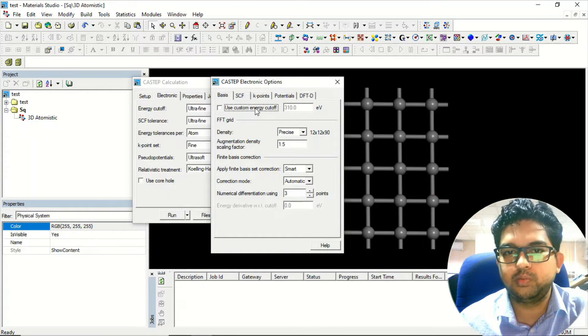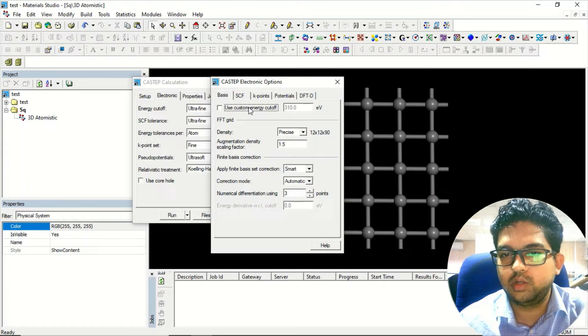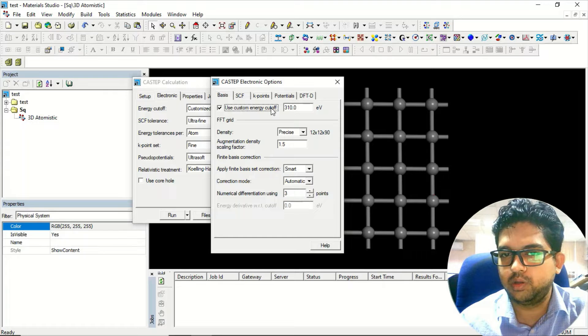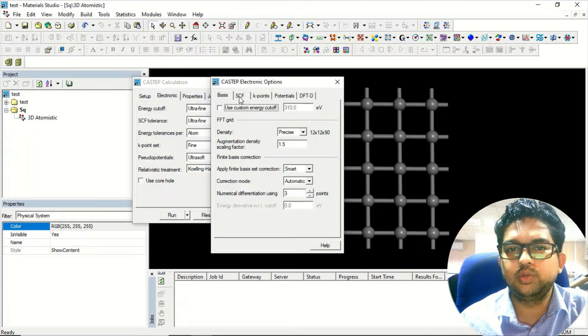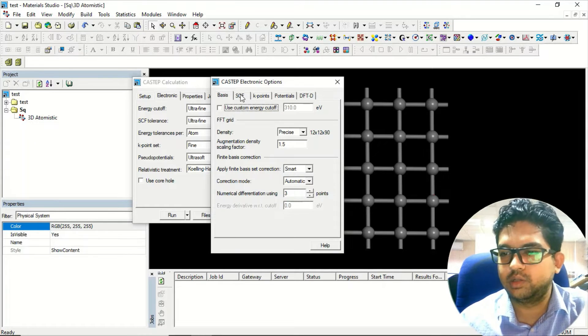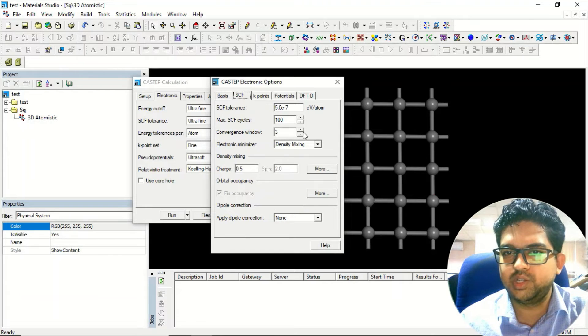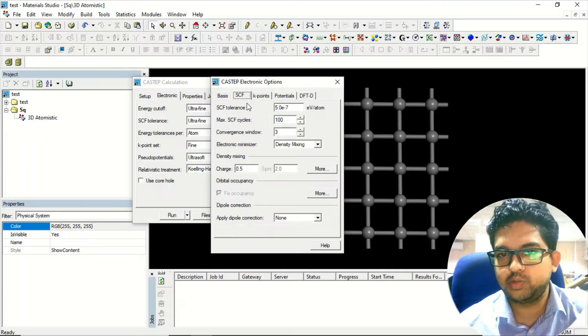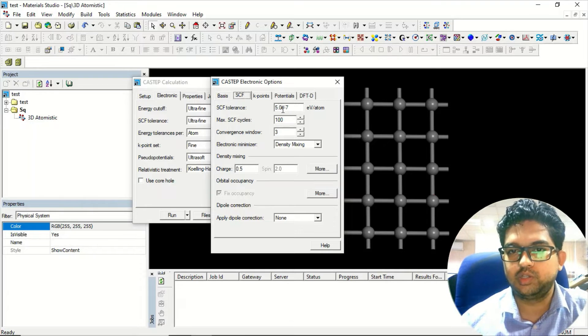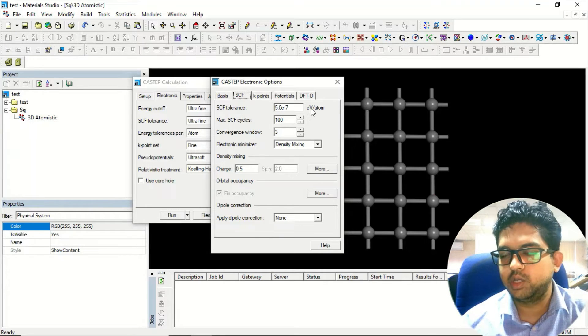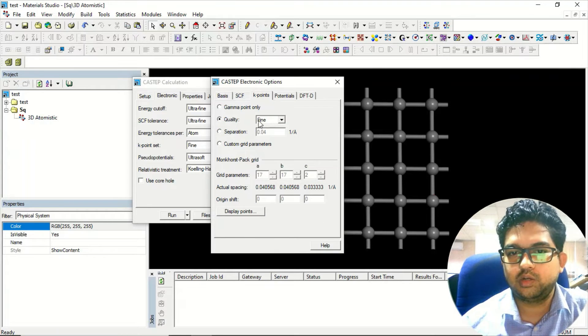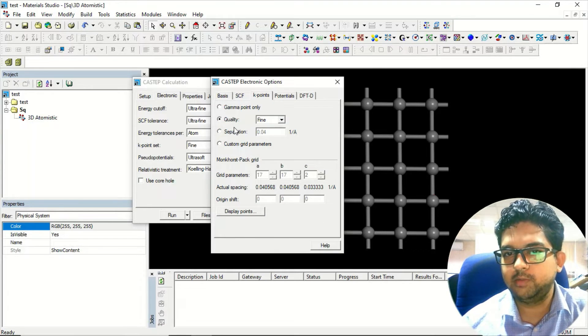Go to the More menu — here is the cutoff energy. In the methodology section of papers you might have seen values like 520 eV or 400 eV; you can manually enter that value here. Right now I'm not changing it, keeping the default. Go to SCF — don't change anything here. The SCF tolerance, as seen in some paper methodologies, is 5×10⁻⁷ eV per atom.